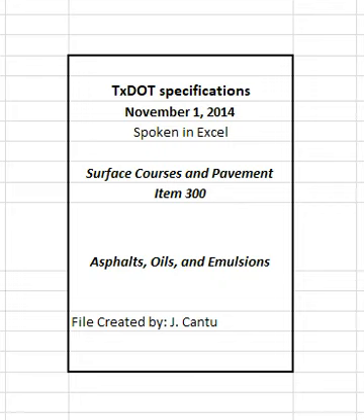1. Exception to T59, bring the temperature on the lower thermometer slowly to 350 degrees Fahrenheit plus or minus 10 degrees F. Maintain at this temperature for 20 minutes. Complete total distillation in 60 minutes, plus or minus 5 minutes, from the first application of heat. 2. HFRS-2P must meet one of either the ductility or elastic recovery requirements.